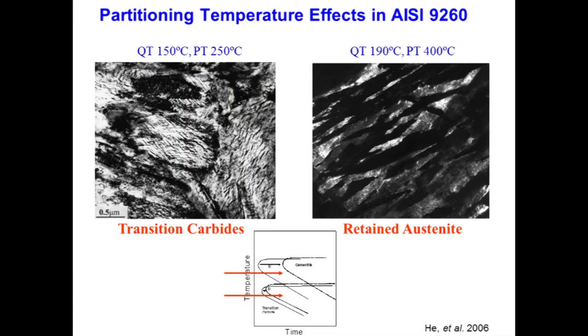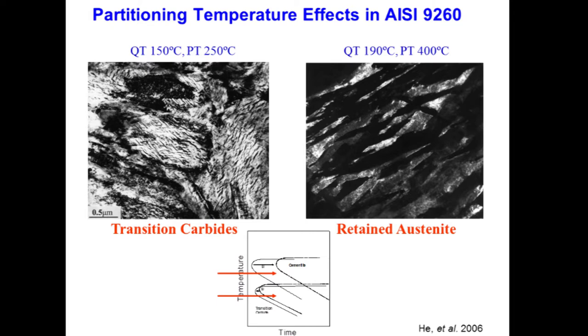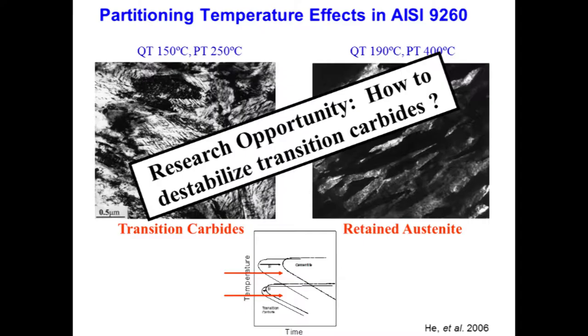We've looked a lot at partitioning mechanisms and some of the physical metallurgy, and the group at Leeds has led us in this regard. One of the questions is about carbide precipitation, which generally speaking we don't want, because it takes carbon from the microstructure that we would otherwise use for austenite stabilization. I'm showing a particular steel that's partitioned at two different temperatures. In one case, we get a lot of epsilon transition carbides in the microstructure. In the other case, at higher temperature, we get austenite stabilization. So for the community, I think one of the challenges is, how do we control the stability of transition carbides other than perhaps temperature, according to the models that we think we understand? If we could turn on and turn off transition carbide formation using other means than we understand now, it would be a powerful alloy design tool.